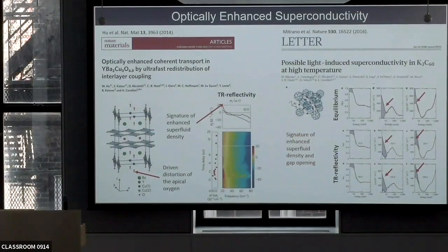And the reason is because, first of all, different technologies are used in building and generating those pump pulses. In both cases, you really would like to probe what happens to the electronic structure away from the gamma point, so close to the zone boundary, and therefore using a very large photon energy, which has so far not been available for this kind of study. So to us, this is a very interesting study that we would like to replicate, but not looking at the time-resolved reflectivity, but really looking at the time-resolved, angle-resolved photoemission signal.